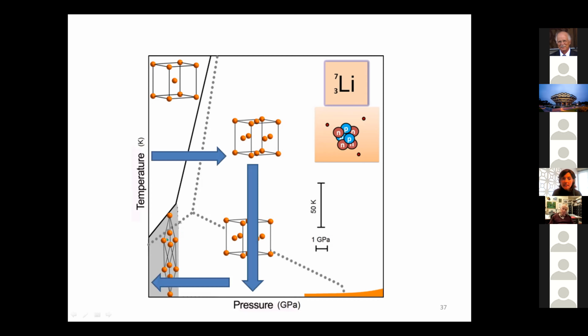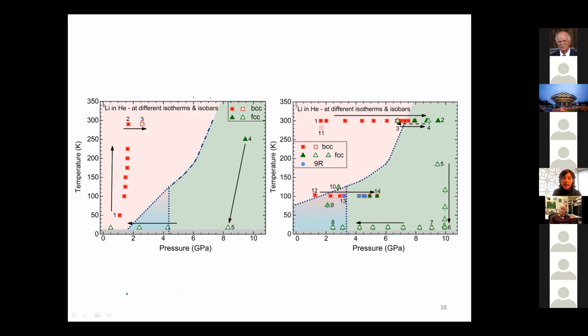What if instead of cooling down, we just go around? First, make sure that lithium goes from BCC to FCC, and this is a high temperature effect. And then we cool down, so you're still in FCC, and then we back off and see if 9R is the ground state, supposedly going back and forth, we should recover some of it. And this is what we did, and here is what we saw. Red is BCC, green is FCC, and blue is 9R. And we see for both lithium 6 and 7, if we pressurized, we go from BCC to FCC, and back and forth we can go between the two phases, cool down, stay in FCC, back off, and even warm up, and we never recovered 9R.